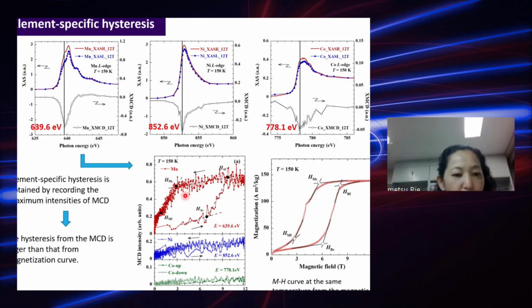It is well known that XAS experiments have surface sensitivity. Additionally, we used a small grain for the magnetic measurement. It may correspond to a single crystalline grain, and we used the polycrystalline sample for the XAS experiments. If the light beam concentrates on one grain, however, the surrounding grains will affect the behavior of the martensite transformation.